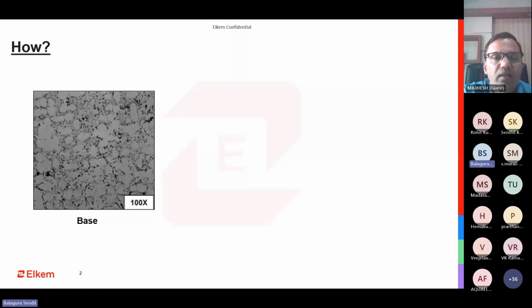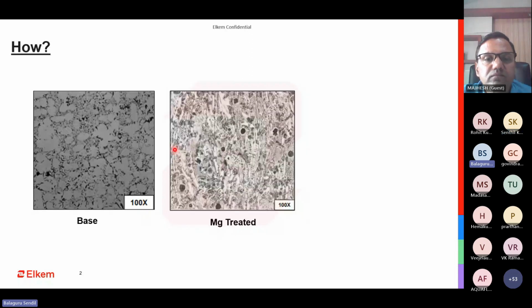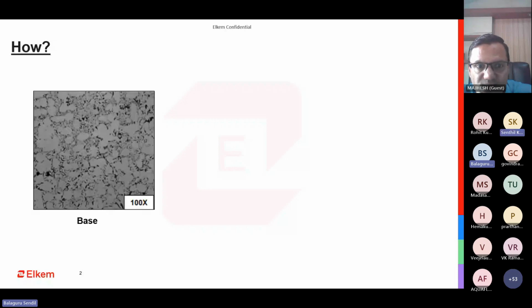Since we have carbon in our base metal, if it is not coming out properly, you will get something like this. This sort of microstructure is quite hard and brittle. It is very difficult to use this material for any engineering applications. Again, with the base metal, the microstructure is something like this, and it will be very difficult to have any engineering application. As such, this material is quite hard and brittle. But when we produce ductile iron, we do a lot of magnesium treatment. Even after the magnesium treatment, the second microstructure looks something like this. You see a bit of nodules, but most of the time there are a lot of carbides. This has improved the mechanical properties to some extent, but it is also not quite usable.